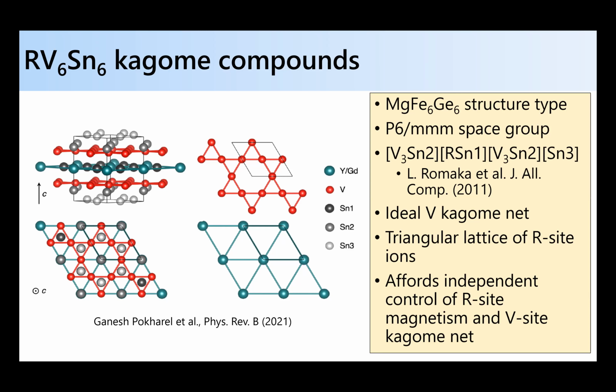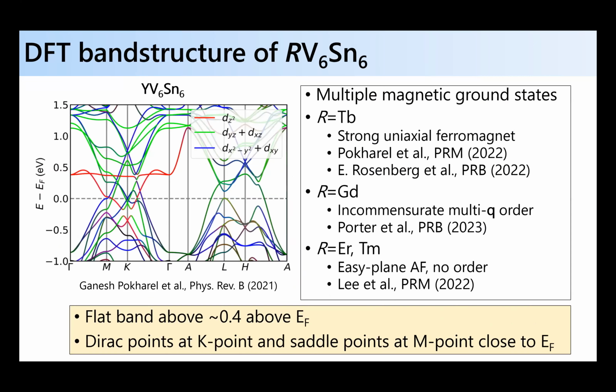Okay, so this is kind of appealing because in the 135 systems, one of the features is that the vanadium-based kagome net is non-magnetic, so you can avoid magnetic instabilities. In this system, you can perhaps reintroduce magnetism or collective magnetic order to interface with instabilities realized in the vanadium-based kagome net. All right.